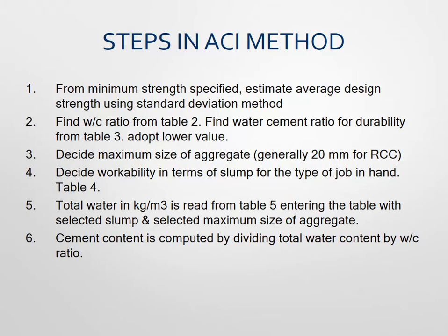The following steps are to be followed in the ACI method. First, from the minimum specified strength, estimate the average design strength using the standard deviation method. Second, find the water-cement ratio from Table 2, and find the water-cement ratio for durability from Table 3, then adopt the lower value. Third, decide the maximum size of aggregate — generally 20 mm for RCC — which depends on the distance between forms, spacing between reinforcement, and thickness of the slab.